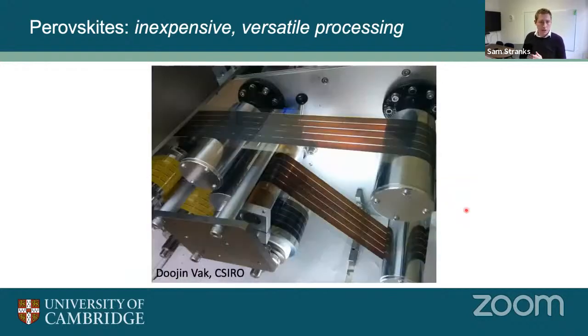And because this can be done at low temperature, it means we can think about processing them on plastic, for example, or on other flexible substrates, and processing them at much higher throughputs. So processing roll to roll, for example, you can think about a bit like a newsprinter, and really printing them at very, very high rates. And this is actually an example of a prototype roll-to-roll printer of perovskite cells. We can see on the left here the yellow of the precursor films, and then they're gently heated, and they form these brown, very dark absorbing cells on the right there.